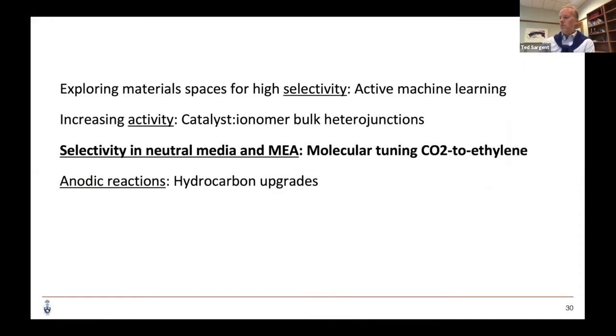Now, I made reference a couple times to the fact that in highly alkali electrolytes, we do a lot of work in KOH, for example, there's a carbonate formation problem, and it happens quite abruptly near the interface. Within a micron, you can be in trouble. And so for us and for many groups around the world in this field, there's an interest in moving towards neutral or potentially down the road to see if we can do acidic CO2RR.